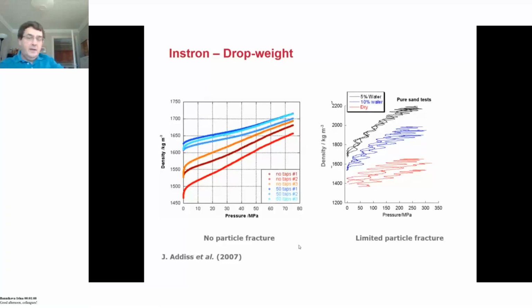But fundamentally, the kind of response you get is very similar to the low density compaction, but the lubrication of the water has allowed some compaction. We recovered again the sand from that condition, and we discovered there was limited particle fracture. So energy being dissipated through particle fracture was not really a significant process in this condition. Mainly rearrangement of particles within the bed was the main thing.